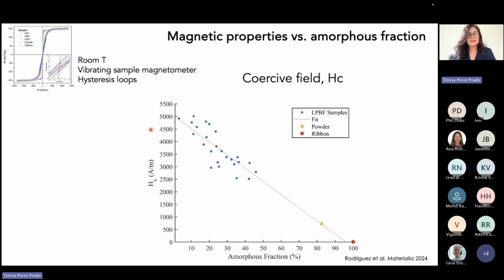First, one last slide. Ultimately, what we want are good soft magnetic properties, because these metallic glasses, iron-based, have very high resistivity. So eddy current losses, this is something where the property is already there. But what we want is to decrease the coercive field. How are we doing there with these commercial alloys? Well, I'm plotting here the coercivity versus amorphous fraction. All these blue dots are the printed cubes under different conditions. And here in red, you see an amorphous ribbon. This is for Cuamet, an amorphous ribbon with the same composition. The coercivity for the amorphous ribbon is about 10 amperes per meter. And look, here we are still, no matter how much we change the processing conditions, at about 2,500. So we were still orders of magnitude away from our target.